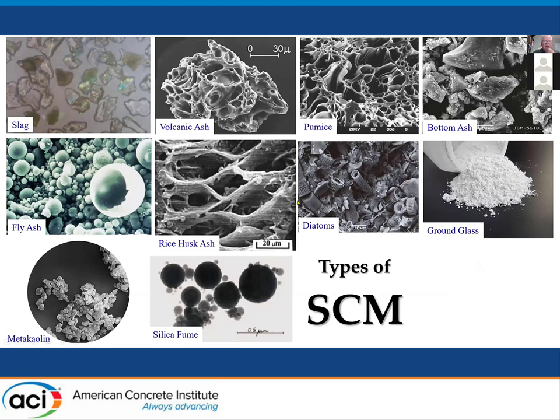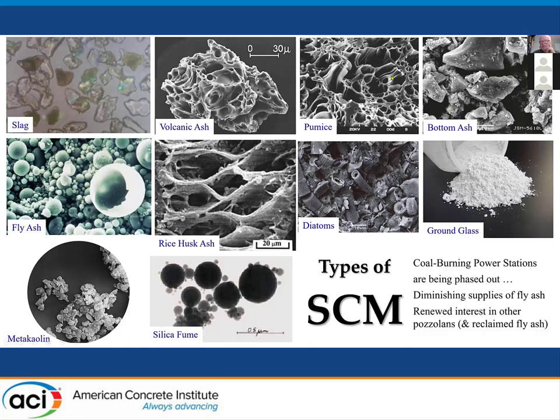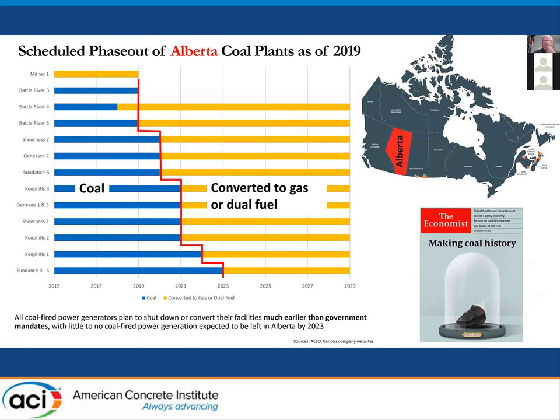So there's a lot of different materials out there as supplementary cementitious materials. We've been using fly ash for years, slag, and now there's a bunch of interest in new natural pozzolans, ground bottom ash, which I'll be talking about, and of course ground glass, in addition to metakaolin and silica fumes. So one of the things that's driving this for bottom ash is the reduction in coal power.